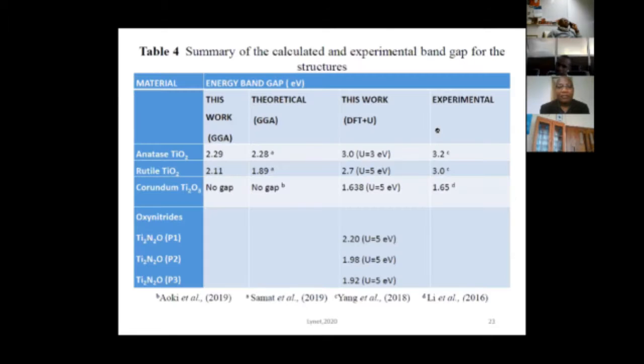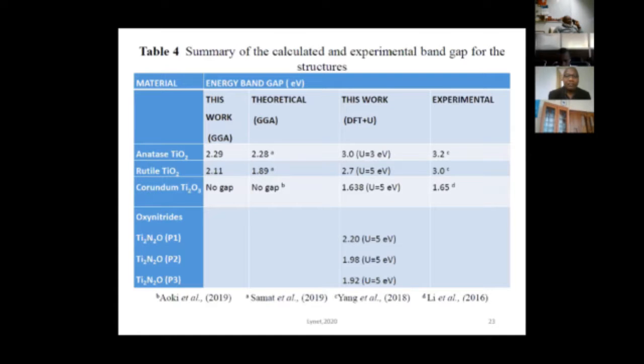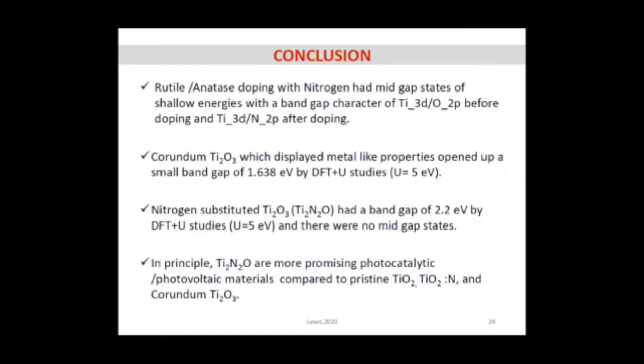So these oxynitrides appear to be more promising photocatalytic or photovoltaic materials compared to pristine nitrogen-doped TiO2 and the corundum Ti2O3. The band gap of the most stable one, P1, was 2.2 eV. Just going back slightly, the band gap is a direct gap of 2.2 eV. This is clearly near the middle of the visible light, so we have a major part of the spectrum being used. And there were no in-gap states, meaning absorption threshold will not be affected when we use this kind of oxynitride. These are some of the references used.